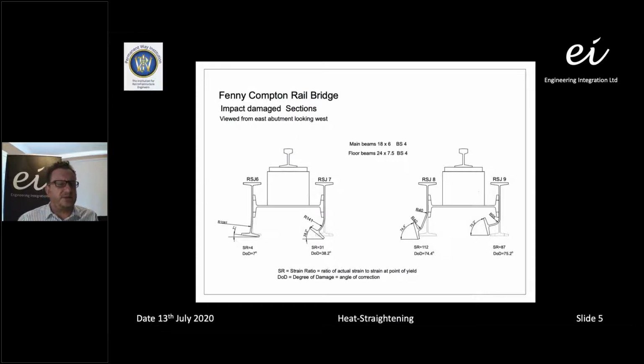When we look into that in a little bit more detail, you can see there that we've actually got significant deformation of the bottom flanges. We believe that this structure was struck by a container being carried on the back of a lorry, and the container impact points are actually quite well defined on the structure, and you can see there that the bottom flange has rotated significantly. We'll come back to that particular structure in a little while, but I just wanted to give you an insight into the type of damage that we're actually dealing with.